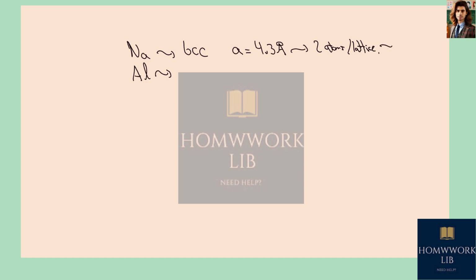Hi, so for solving this problem, the first thing that we need to have as information is the crystal structure for each, sodium and aluminum. In the case of sodium, the structure is going to be a BCC structure. We know that the lattice constant is going to be equal to 4.3 angstroms, but this implies that we have two atoms per lattice. And each sodium atom only has one conduction electron.